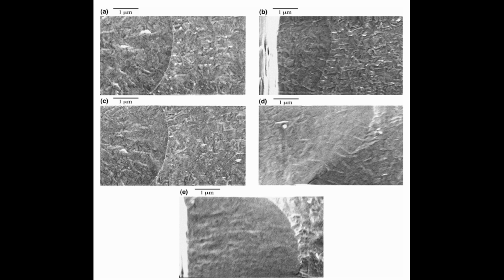But perhaps just as importantly, they uncovered significant variability in the material's strength at this scale. That low Weibull modulus. Right, and that finding spurred them to develop this potentially even better, more consistent testing method. It really highlights that for MEMS design, you can't just know the average property. Understanding the variability is absolutely crucial for reliability.